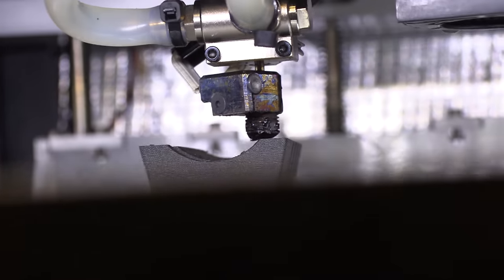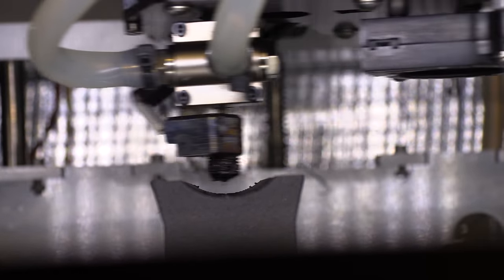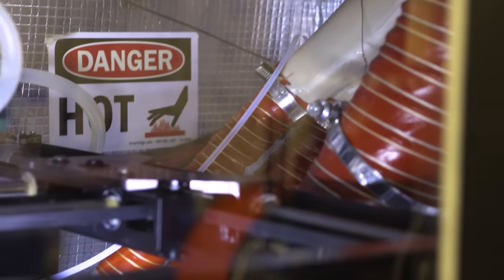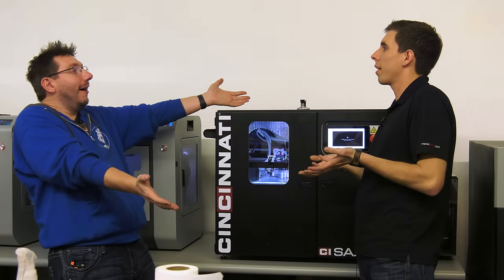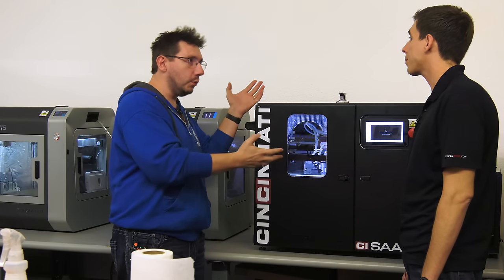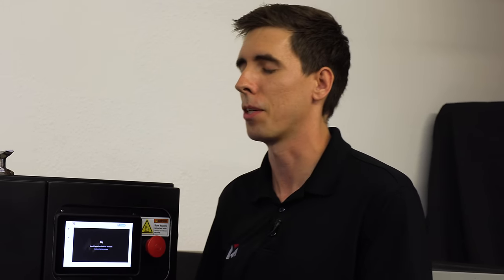The chamber right now is about 110 to 120°C. We've been experimenting cranking it past 140 up to 160 and above — it's literally an oven at this point. Inside there are pipes and tubes, and that's water cooling on all the stepper motors and the extruder itself, because you're in a chamber that's so hot. Anything over 80°C and you start to see skipping, electronic errors, and whatnot. So active cooling on the electronic components is very important.